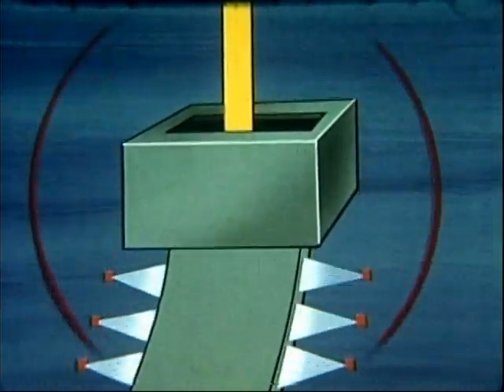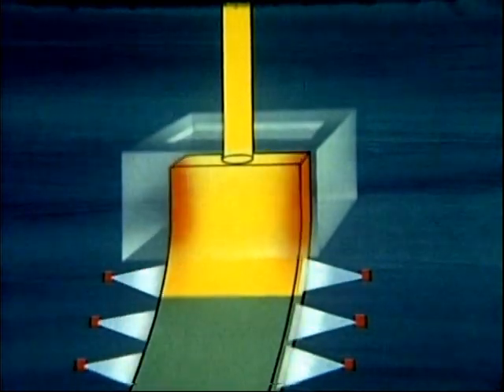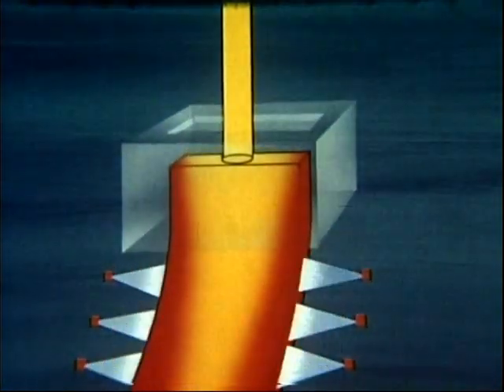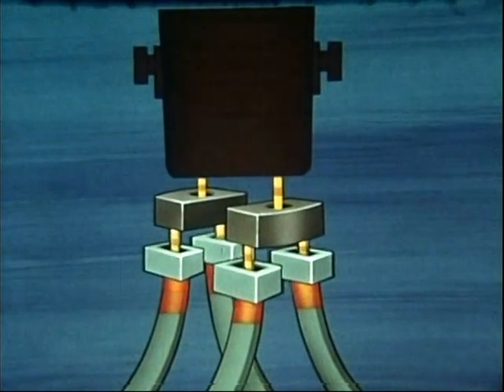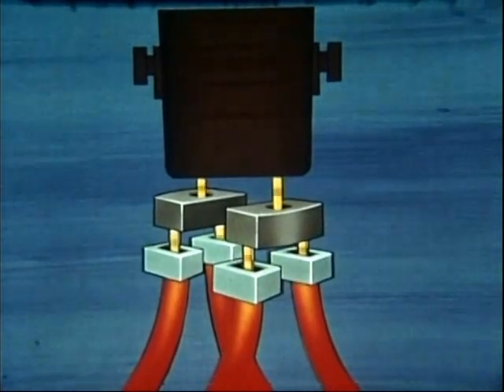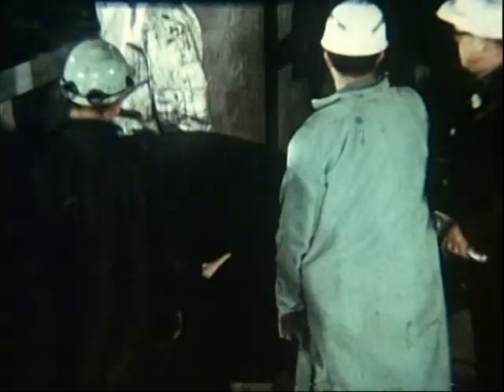Here's where continuous slab casting becomes as precise as a micrometer. Molten steel must stay in that mold long enough to form a safe, self-supporting skin, but it must emerge promptly so the water sprays can solidify it before it reaches the pinch rolls less than 40 feet away. At National Steel this means a speed of about three feet a minute in each of the four molds — 12 feet of slab a minute. It takes just about an hour to convert 330 tons of furnace-hot steel into high-quality slabs. The old ingot and rolling mill method takes at least 12 hours. The steelmen of Weirton still enjoy a sense of excitement with each pour; they know they are pioneers in perfecting this technique, and some experts said it couldn't be done on a production basis.